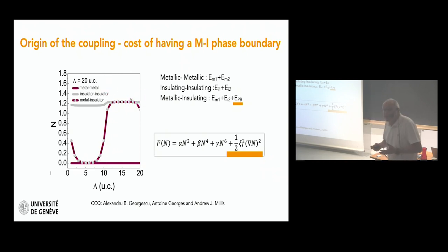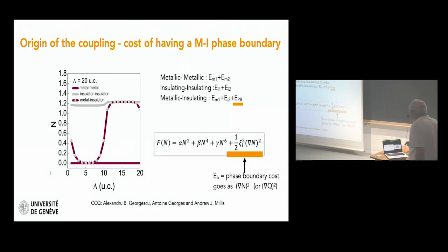And now if you do an expansion of the energy, you write something like this with n squared, n fourth, and n sixth terms. But now if your order parameter varies in space, you have to introduce a term which is proportional to the gradient of this order parameter squared. And this is the term which is written here. This is simply saying that bending the order parameter costs energy. And so we believe that this phase boundary cost is what is controlling the coupling. And you can write it as gradient n squared or gradient q squared.